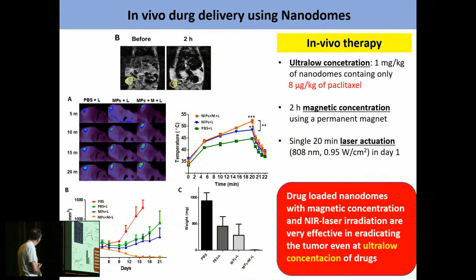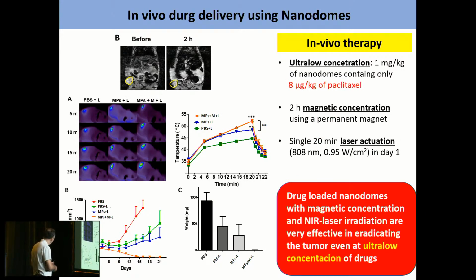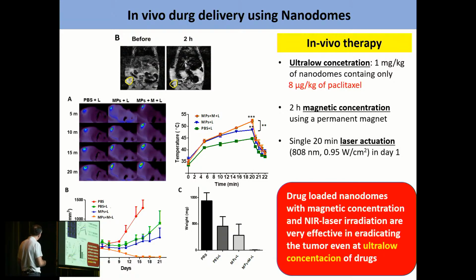And then we did some in vivo tests. First, it's important to mention that we use an ultra-low concentration of both nanoparticles and drugs. We use only about 8 micrograms of Paclitaxel per kilogram of weight of mice. This is about some hundreds of times less than what is usually used in in vivo experiments without nanoparticles.